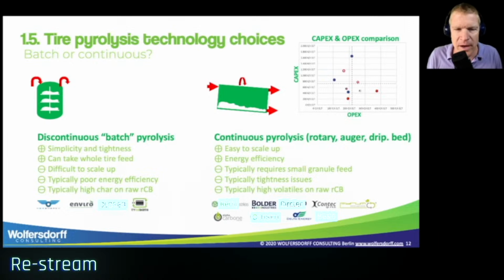One example is Pyrolyx, and for the capacity of 36,000 tons of tire feedstock, they required 20 kilns. Now they have an automatic feeding system, but these are considerations for large scale. Probably a continuous system is easier to set up and to scale up. Typically, the batch kiln has poor thermal efficiency, because to unload the batch kiln, we need to cool down to open the kiln and get out the metal and raw recovered carbon black.